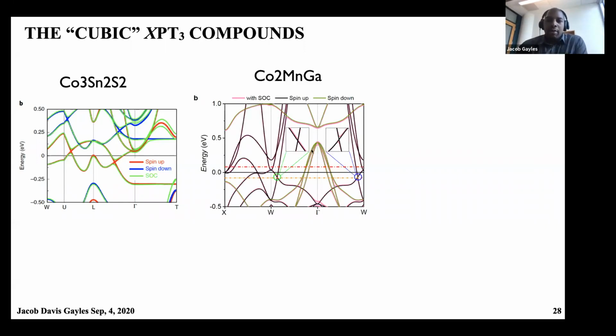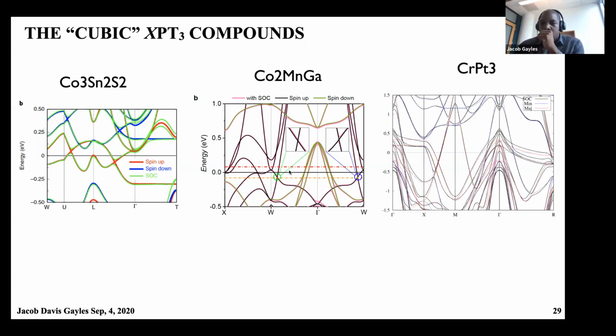And here we also show for the cobalt manganese gallium, which also shows this gapping of the Weyl points. And also, it's not a drastic change here. Whereas the chromium platinum 3 actually has quite a drastic change due to the spin-orbit coupling of the platinum. And this also causes this large orbital moment that you see in the system.